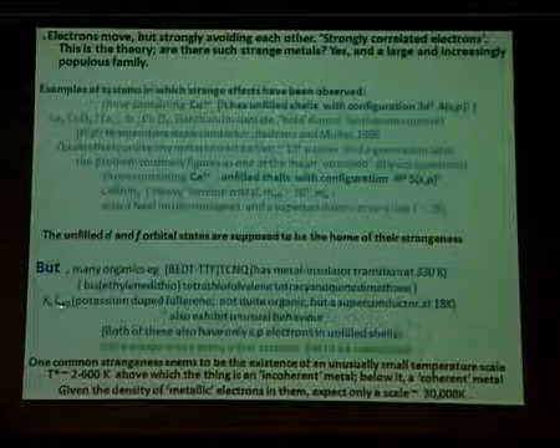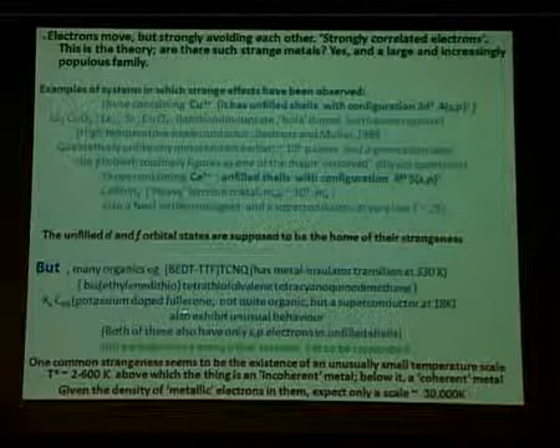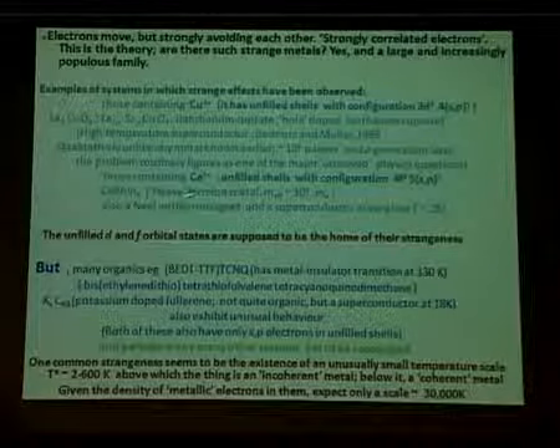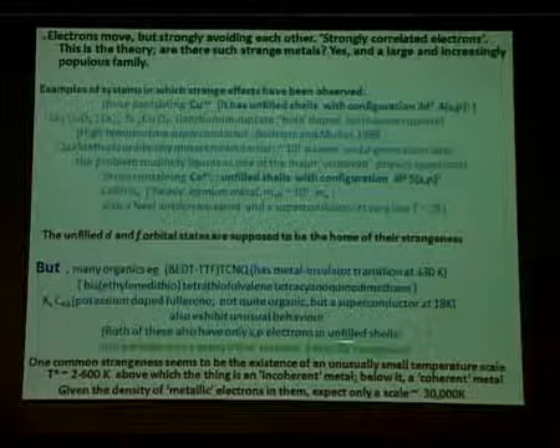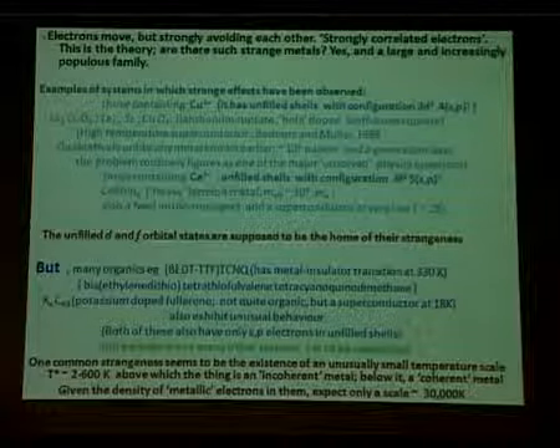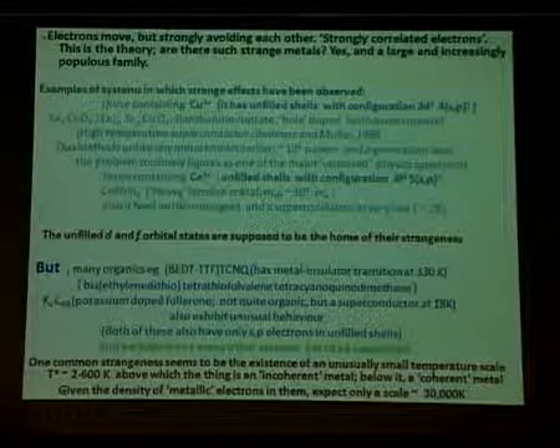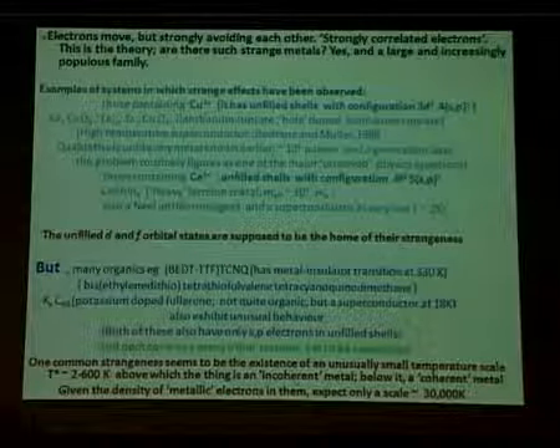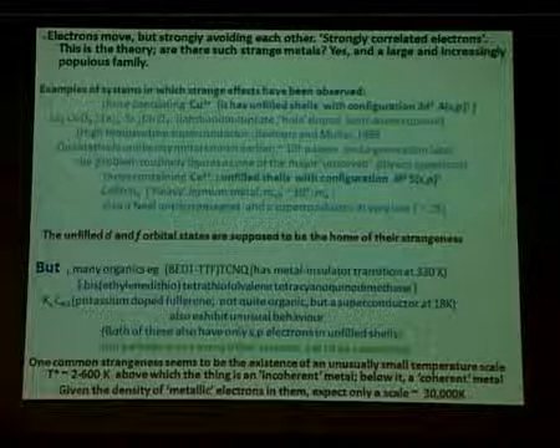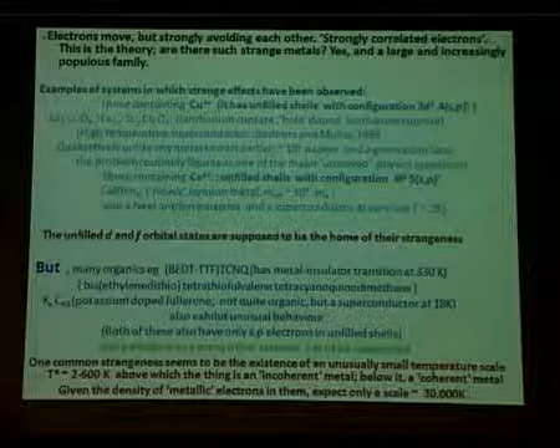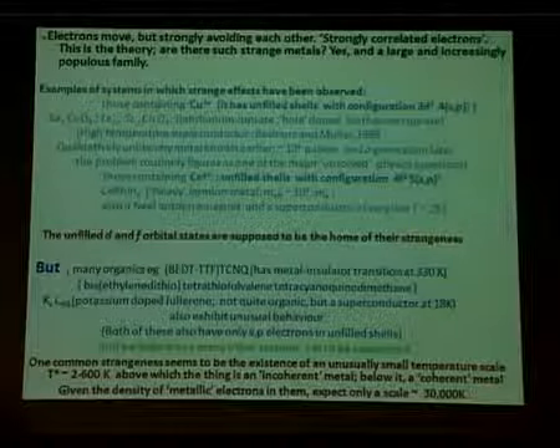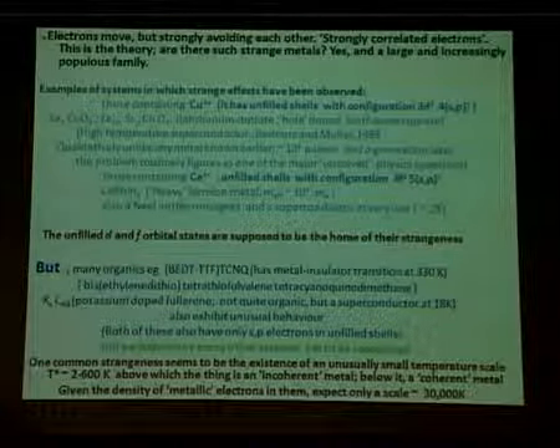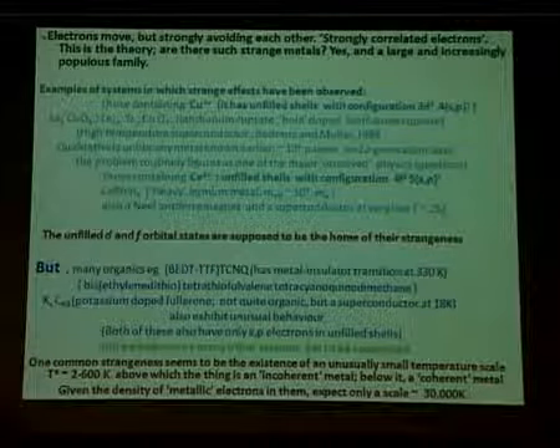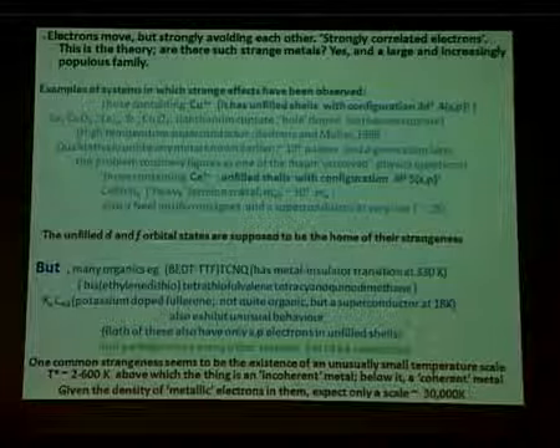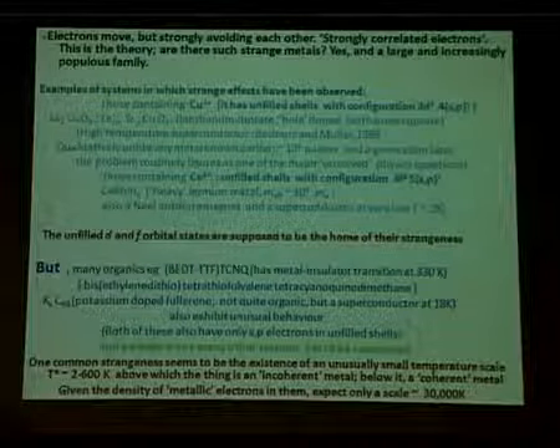Another example is C60 doped with potassium. This is not quite organic, but it's a superconductor at a very high temperature. Neither of these has d or f electrons. They only have sp electrons in unfilled shells. So the conclusion I can draw is only this, that there are many systems which we actually don't recognize, which may be very strange, and the source of their strangeness may be that the electrons in those systems move, but in a way which is not like that of an ideal gas of electrons, and may be very strongly and qualitatively influenced by the fact that they are strongly correlated.